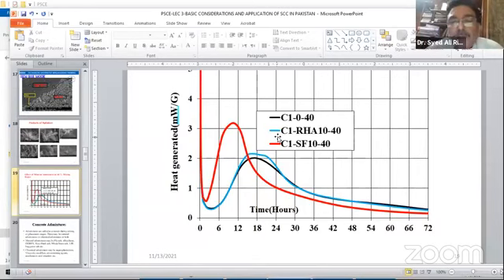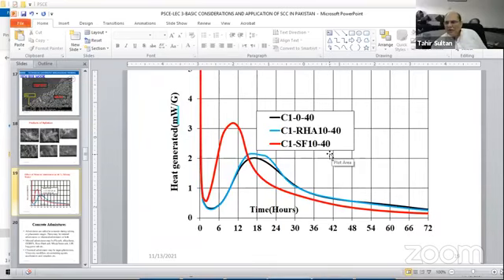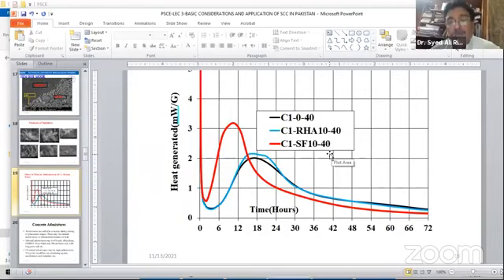Yes. Silica fume is a kind of accelerator. If you see this present investigation, you will see that he is right, Haziq. According to my experience and testing, the maximum quantity of silica fume or rice husk ash or fly ash which should be substituted for cement is around 10 to 15%. For silica fume, 10% seems to be a reasonably good value. So all pozzolanic materials are in fact accelerators. They increase the heat of hydration and the reaction of hydration.